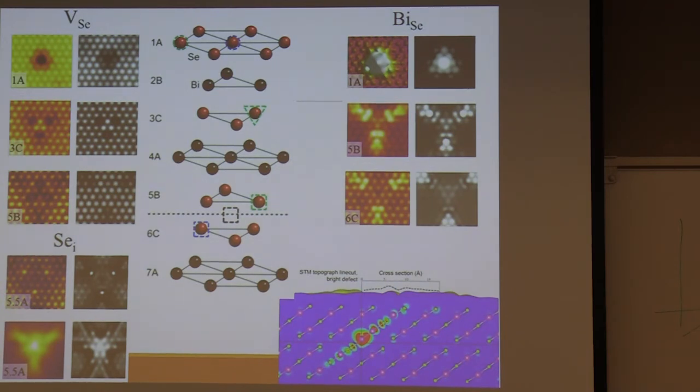Because the question is, you have your N equals number of sites times this Boltzmann factor. So the question is, what's our temperature? Right, what is the temperature? When you think about it, maybe growth temperature. At growth temperature, species are mobile. So you can imagine that you can reach thermal equilibrium at a high temperature. But if we suddenly quench it, all the defects get trapped.